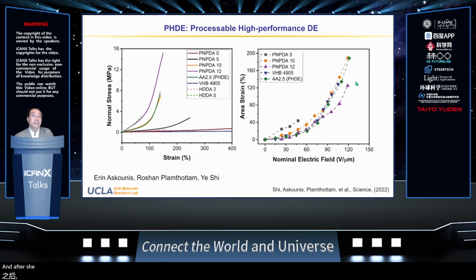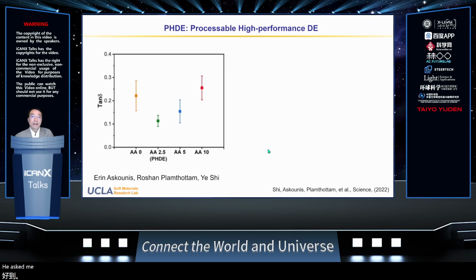And actuation wise, the orange and the green curve here show similarly high actuation strain at a nominal field of 120 volts per micron. At this kind of strain, the true field is more than 300 volts per micron. So this kind of polymer, in particular this system, the green curve, containing 2.5% acrylic acid, we call the PHDE, or processable high performance dielectric elastomers. I'll talk more about this.